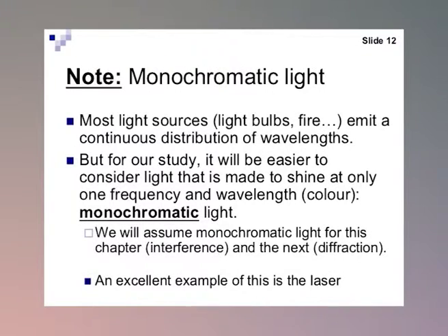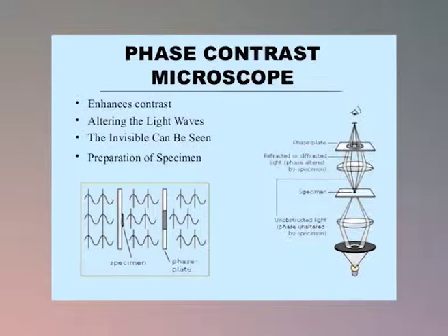This slide with the liquid is then inserted into the hot stage and is illuminated using monochromatic sodium light with a wavelength of 5890 angstroms. The temperature of the hot stage can be controlled for heating as well as cooling with a precision of almost 0.2 degrees Celsius or better. For taking the observations, a phase contrast microscope is used.